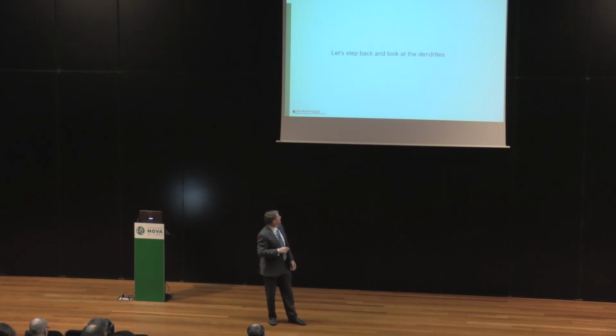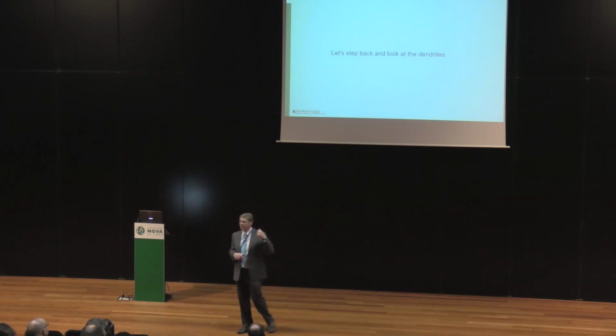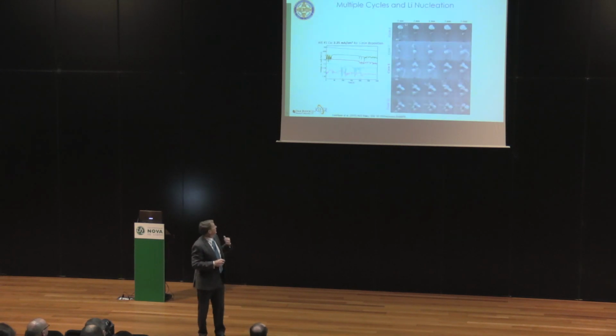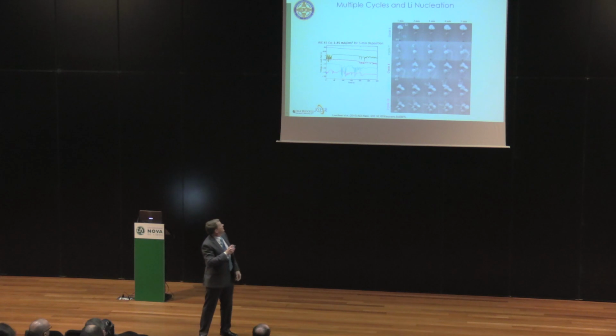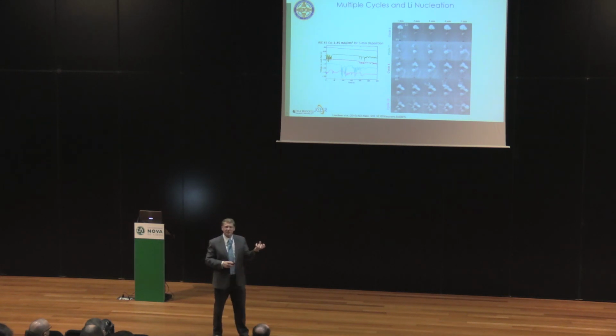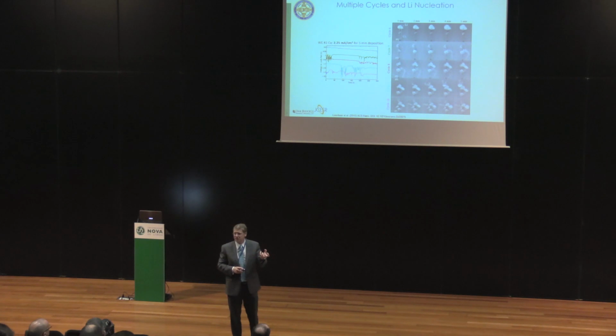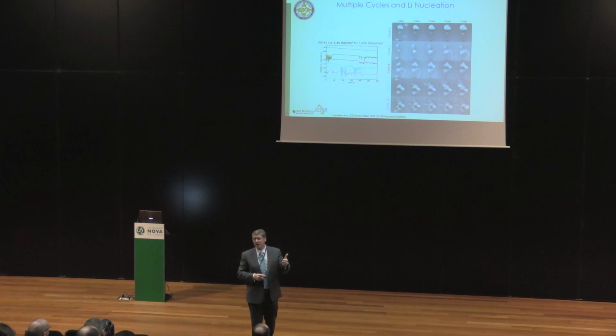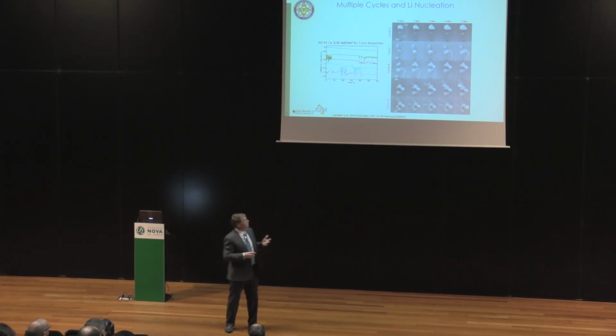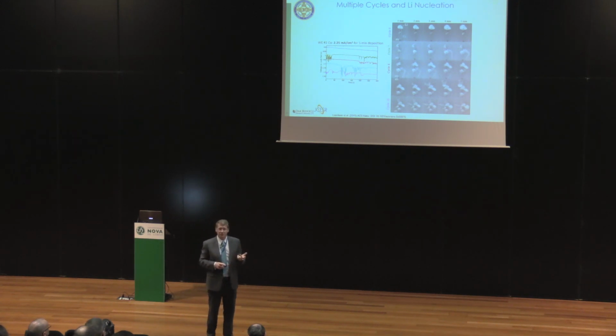All right, so let's take a quick step back and look a little bit at those dendrites. Here's a series of images. Initially, we saw this nice fairly globular structure prior to taking images. They started taking images, and you can see after the first cycle, you have dendrites that are now forming. So high plating rates cause dendrites to grow. Also, taking images with the TEM is clearly inducing these dendrites.